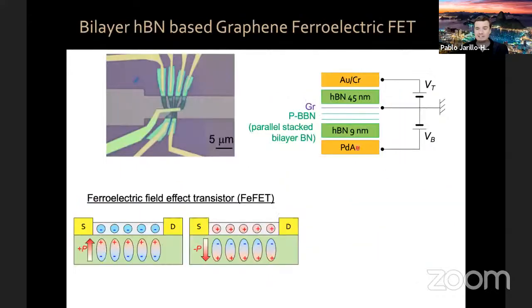So what we did is, let's see if this actually works. We took a monolayer of hexagonal boron nitride, we broke it, and we placed it on top of itself with a 0 degree angle. That's the parallel stack bilayer BN. And then in order to detect this ferroelectricity, we placed a layer of graphene on top. This is embedded in thicker hexagonal boron nitride, and we have a dual gate geometry to apply an electric field so that we can switch the ferroelectricity. So we made, in other words, a ferroelectric field effect transistor.